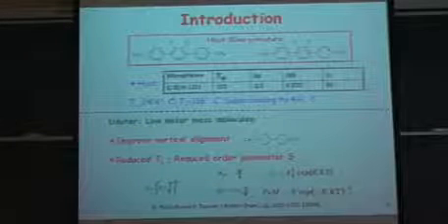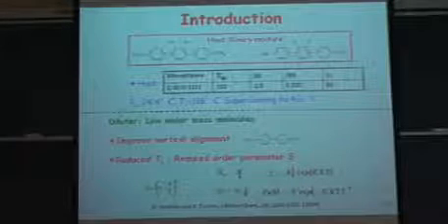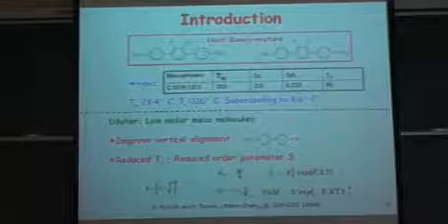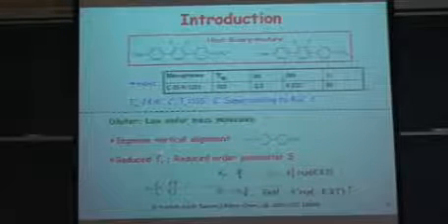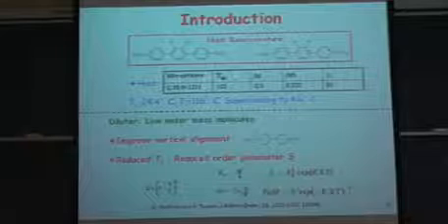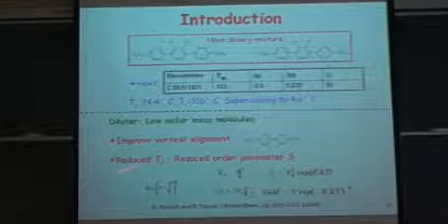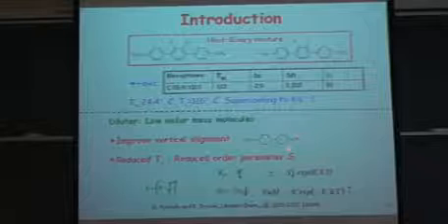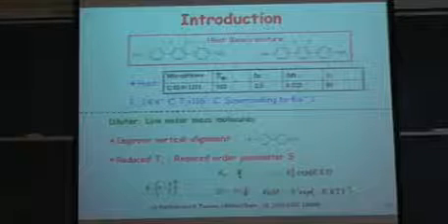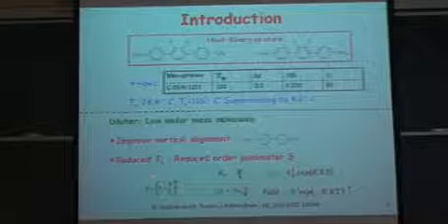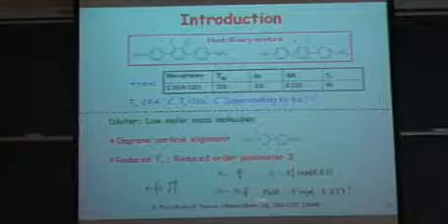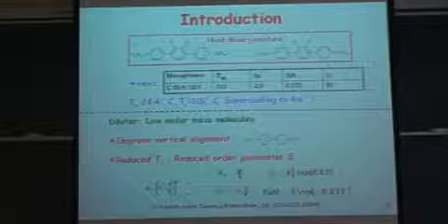And we dope diluters. For example, this one, cyclohexane, has two effects. First, it improves the vertical alignment of a negative liquid crystal. And secondly, because the small diluters can reduce the clearing point of the system, it actually modulates the order parameter. We will introduce this later.